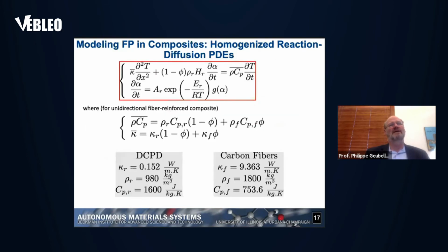So coming back to the formulation that described the process itself, well, we basically extended the reaction-diffusion equation by just using a homogenized model. That's probably the simplest way that we can capture this. So now we have the same reaction-diffusion equation, except that now we use these homogenized properties for the thermal conductivity, the specific heat, and so on. And phi now is the quantity that describes the fiber volume fraction.